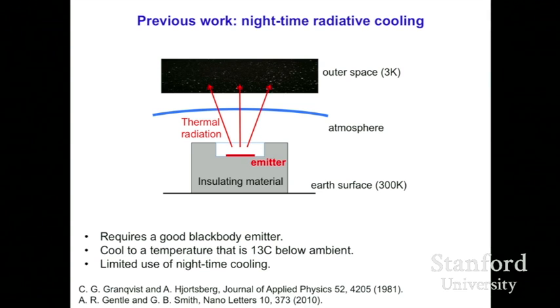Now, in an early experiment carried out almost 40 years ago, it was shown that it's relatively straightforward to cool this emitter down to a temperature that's about 13 degrees below ambient in an entirely passive way. So this actually is a technology that's available. Apparently, one of the buildings here at Stanford used this to produce cold water at night. But it has not been a very widely adopted technology for cooling purposes.